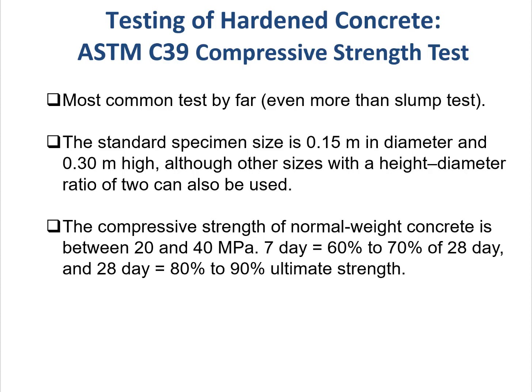The standard specimen size is 6 inches in diameter and 12 inches in height, although other sizes with a height to diameter ratio of 2 can also be used. We require the height to diameter ratio to be 2 because we want to eliminate the end effect due to the friction between the loading heads and the specimen. We want to produce a zone of uniaxial compression within the specimen. If the height to diameter ratio is less than 2, then a correction factor should be applied to the results. You can check the correction factor in ASTM C39.